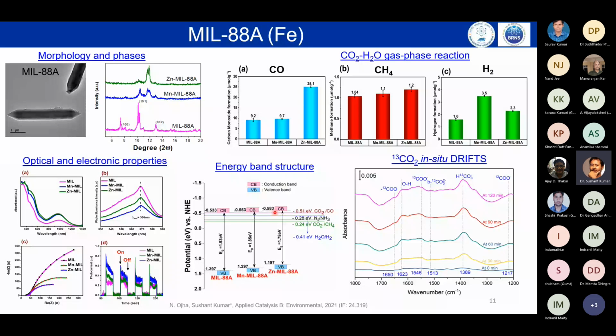So the conduction band position was minus 0.583 compared to minus 0.553 for the manganese. And there is an upshift for the valence band, saying that the zinc would prefer more of the reduction capacity. So here we have performed the tests, and what we have seen is more CO formation in such cases when we have the zinc.